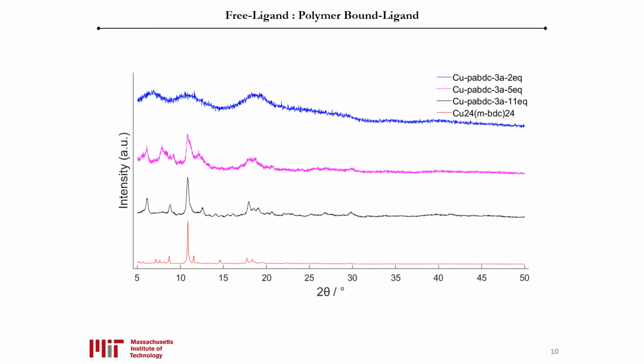After crystal formation was observed, the polymer was then incorporated with the metal organic cages. We completed 3 separate reactions of stoichiometric ratios for free ligand to polymer bound ligand. The ratios were 2:1, 5:1, 11:1 free ligand to polymer bound ligand.